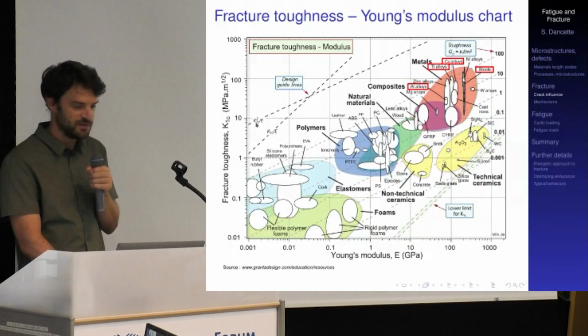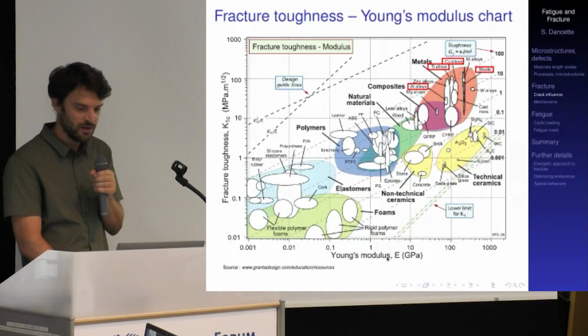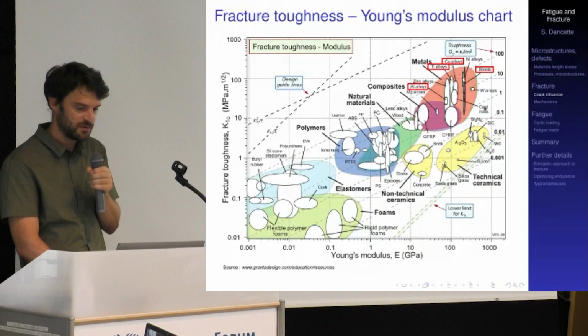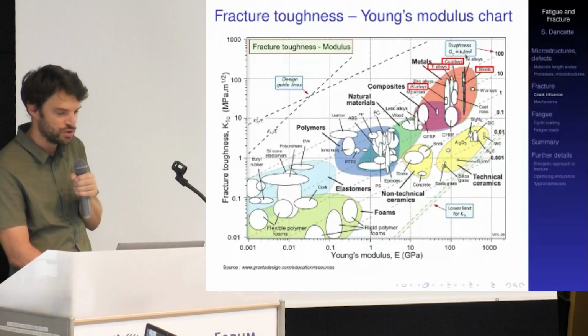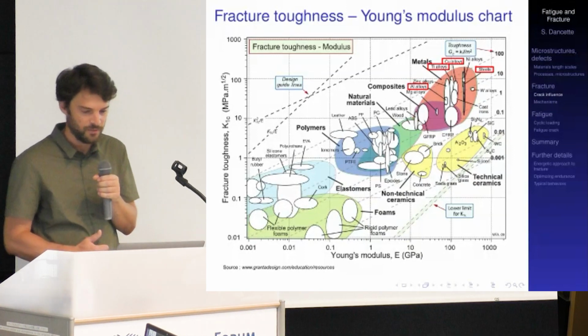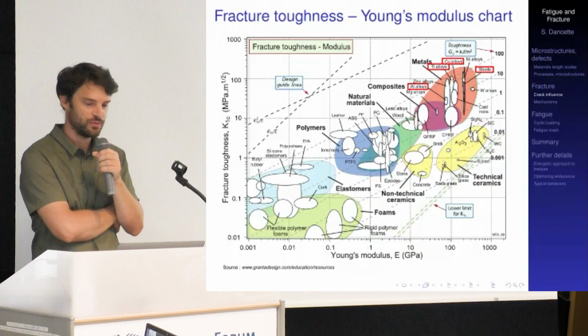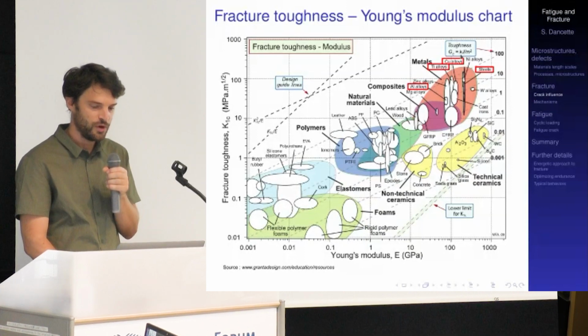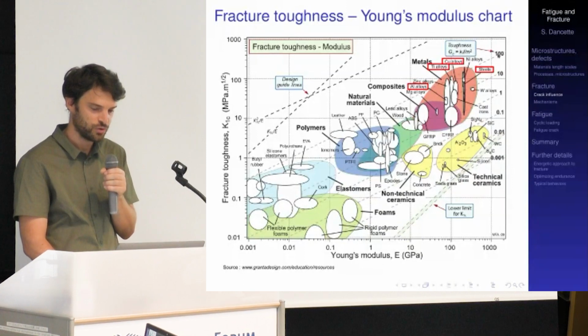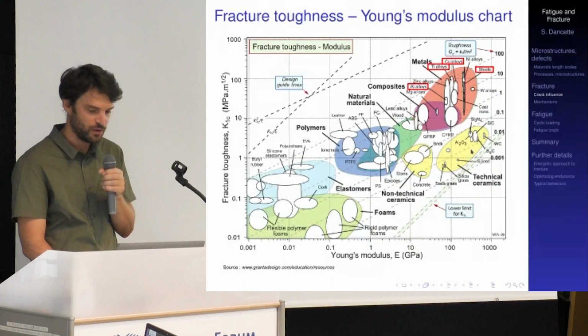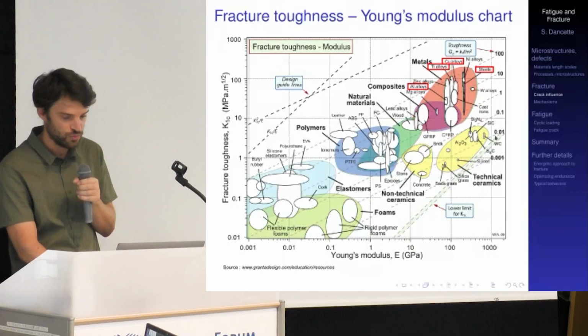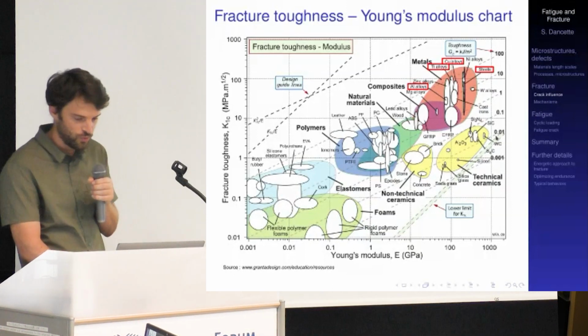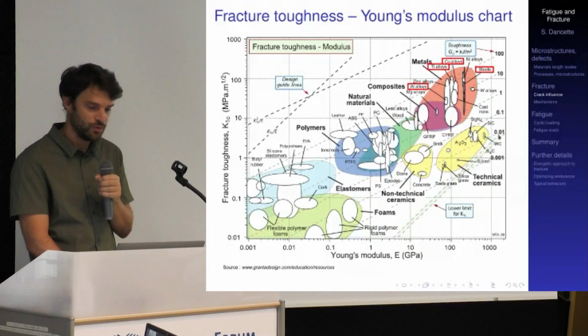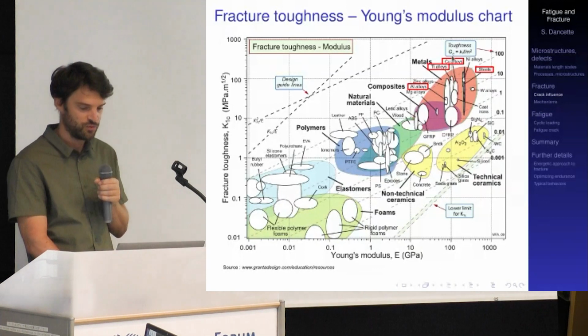And if we relate these two values, fracture toughness and Young's modulus, when you look at such maps, these so-called Ashby maps, you can come up again with an estimate of the toughness itself, in terms of energy per unit area dissipated in fracture. So in terms of energy per unit surface, some of the metals have fracture energy as high as 100 kilojoules per square meter, while some of the most brittle materials, such as ceramics, have fracture energy as low as 0.01 kilojoules per square meter, so a few tens of joules per square meter.